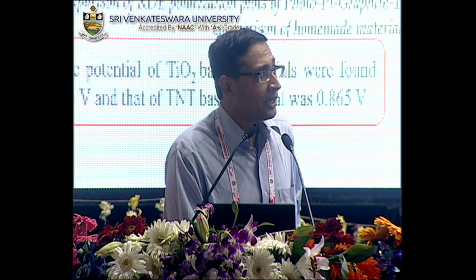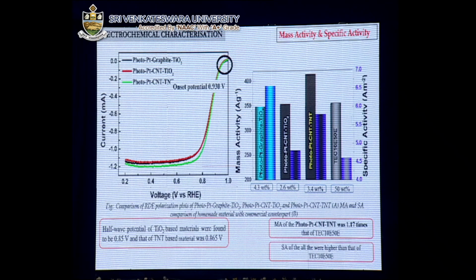And finally, summarizing the overall effectiveness of this method and the electrocatalyst, we see that these are various quantitative measures to prove that the catalyst is good and workable as an electrocatalyst. We see that the graphite based electrocatalyst is on par with or a little more than the commercial catalyst with 50% platinum, and the CNT based catalyst is far higher and is almost touching the range which the DOE, the Department of Energy, has projected now.